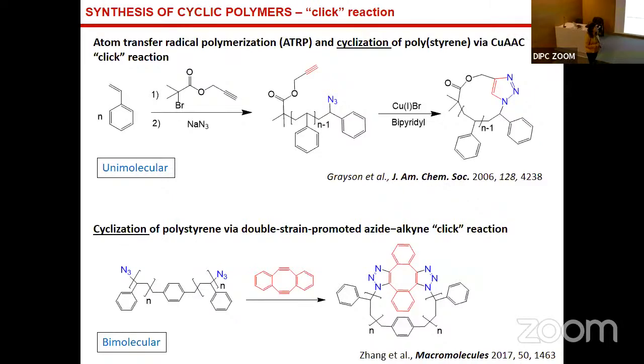And this is one of the typical click reactions. This is a copper catalyzed azide-alkyne cycloaddition. This is the reaction of this alkyne with this azide to form this triazole. The good thing of this is that you can synthesize the linear polymer by any polymerization technique. In this case, they use atom transfer radical polymerization. The incorporation of the end groups is already here in the initiator of the polymerization. Then the bromide that appears here was modified by azide. This is an example of unimolecular reaction. It's only one molecule with two different chemical groups.